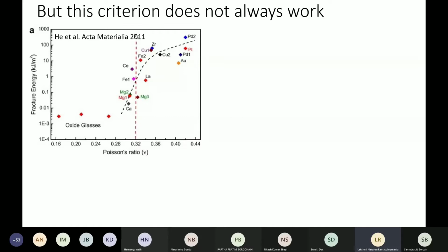But if you look at some of these small data points on the top right side, you see gold-based metallic glasses have very low fracture toughness, whereas palladium-based glasses are almost as high as 200 MPa root meter, sorry, not that, 200 kilojoule per meter square. Your gold-based metallic glasses are only 10 kilojoule per meter square. This is the fracture energy, another way of representing your fracture toughness. So gold doesn't really follow this rule, because according to the Poisson's ratio rule, the higher the Poisson's ratio, the higher the fracture toughness. So it obviously does not follow this particular rule.